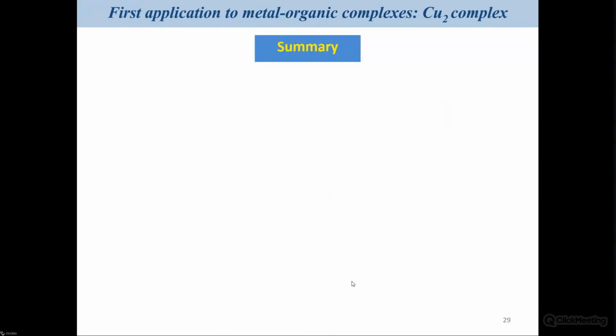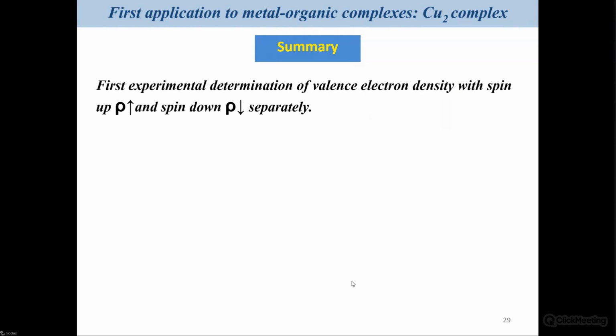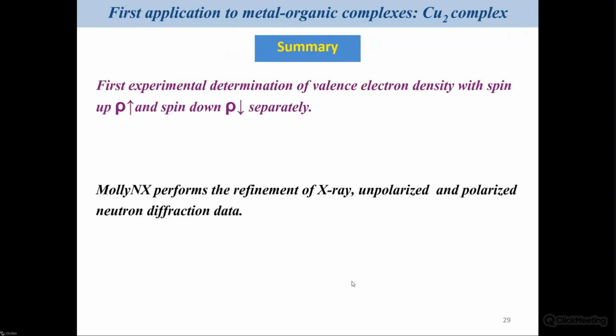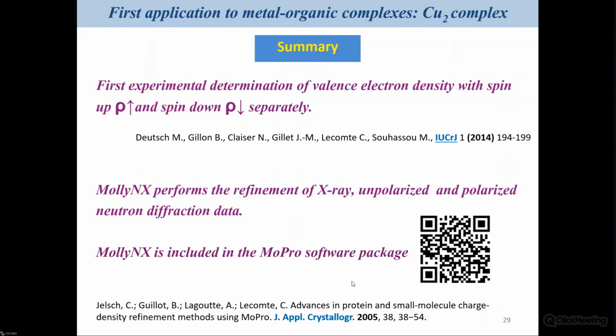So to conclude on that first part, it will be the demonstration that it's possible to combine different kinds of experiments to be able to refine experimentally spin up and spin down population on that system. For that, we developed a specific program. We call it MollyNX, for the refinement of X-ray, unpolarized and polarized neutron diffraction data. And of course, MollyNX is now included in the MoPro software package distributed in our lab.